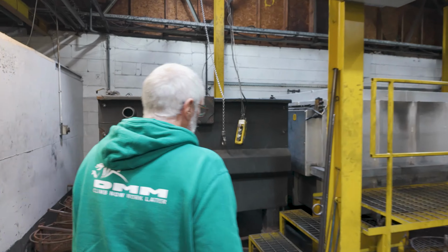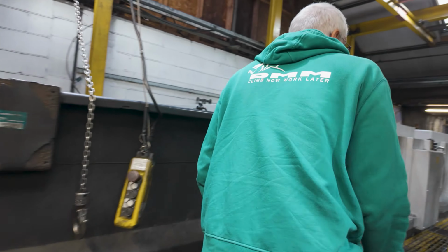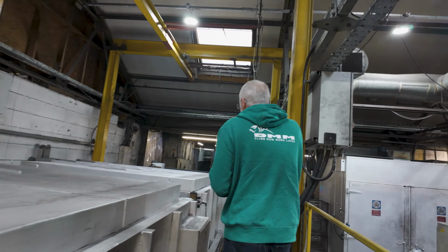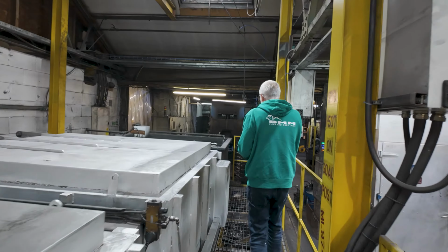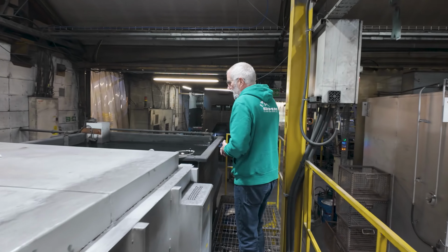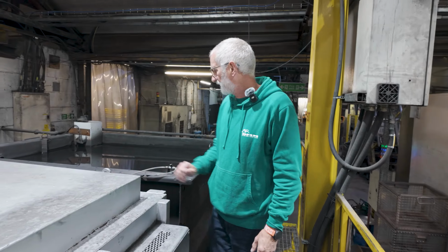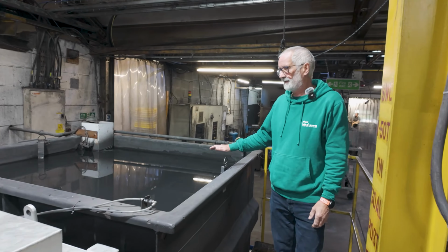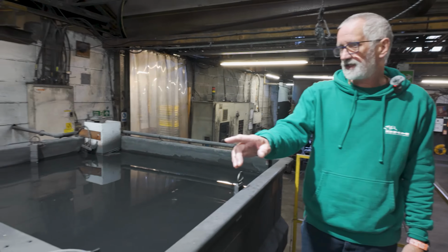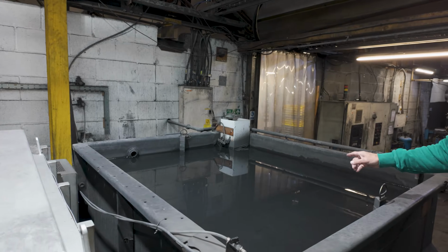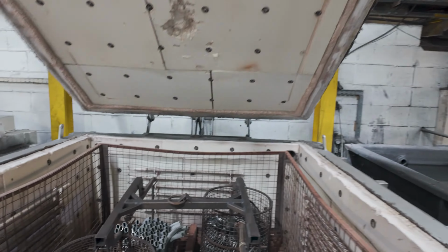Now, both these processes are completely controlled by a PC. We're working between plus or minus 1 degree Celsius, and the times and the temperatures are absolutely important. They're crucial in terms of getting the right strength. So we'll take a look at the two big solution treatment furnaces here, and these will actually accommodate up to 4 batches of carabiners. That's over 3,000 carabiners. So this is the actual furnace, and this is the quench tank, and the product will come out of the furnace and into the quench tank in a very short space of time.